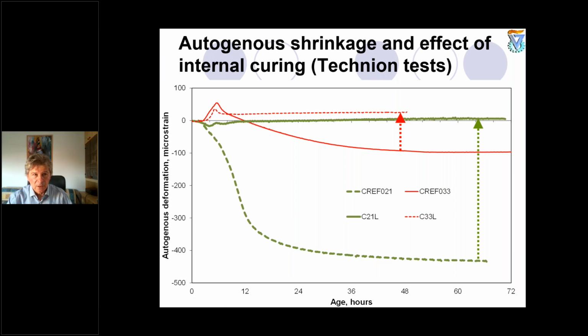And then please look what we have in the experiments with concrete after adding this pumice. Let's say we have reference concrete made of very low water-cement ratio, 0.21. This is a dashed curve here. Extremely high autogenous deformation, in microstrain. You can easily see it reaching almost 500 microstrains. This is a reference. If we have higher water-cement ratio concrete, for example, 0.33, we still have some autogenous deformation, and this is not good. But